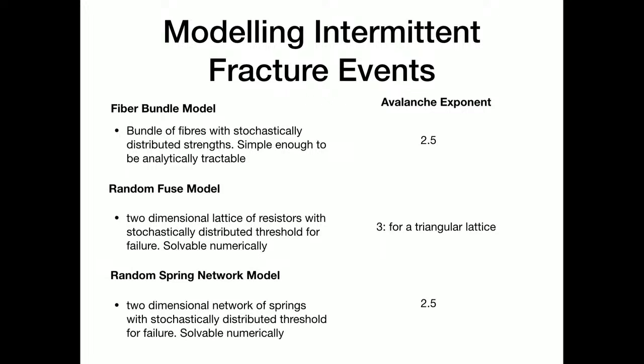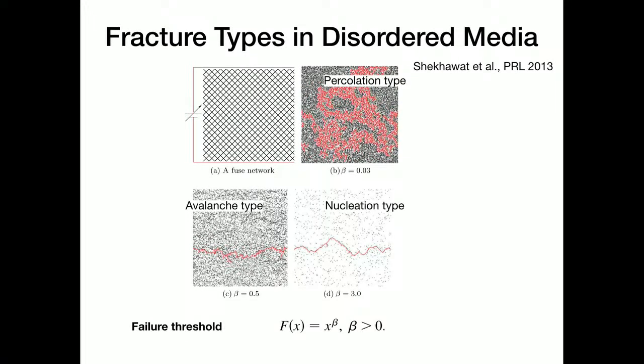For instance, is this avalanche statistics behavior universal across all disorders? No. You see that depending on the extent of disorder, you see different types of fracture behaviors. And in this study with a fuse network, essentially you increase the current passing through the network of resistors, and all of them have a threshold, which is from this power law distribution, and when it's exceeded, it burns out and stops conducting, and you have initiation of damage there. And if the damage is such that the network stops conducting, you say it's failure.